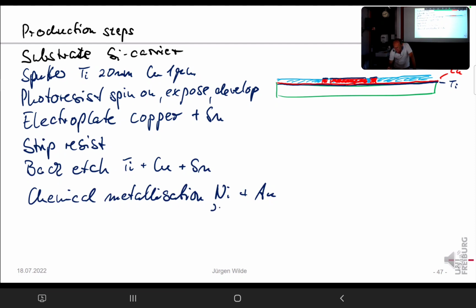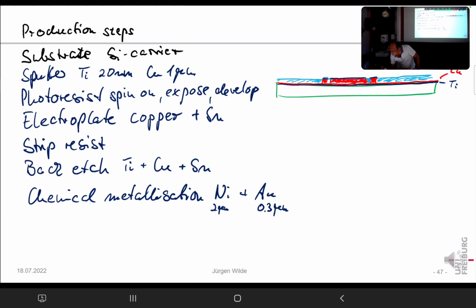For instance, nickel 2 micrometer and gold, let's say 0.3 micrometer or so. That's quite different, but it's a thin gold and a thicker nickel. The reason is wire bondability. And also we have solderability. So that's the substrate.